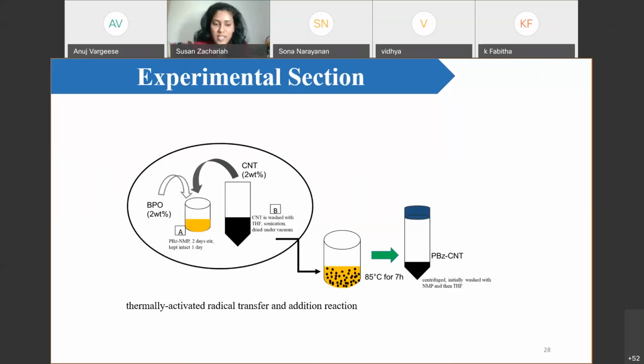So this is the experimental section. First, we prepared a polybenzoxazine solution with NMP, and CNT is added to it. We also added BPO to enhance the reaction. Finally, we got a CNT functionalized with PBZ. This PBZ functionalized CNT is used as a reinforcement to the matrix, which is the PBZ solution. These PBZ-CNT particles have been added to the PBZ solution and stirred, and this solution is used as a coating.